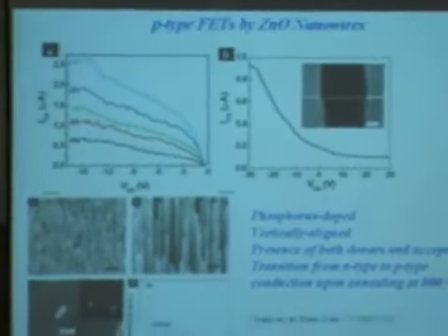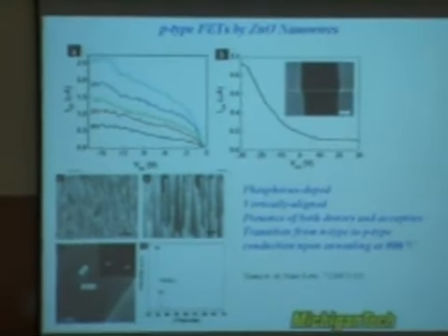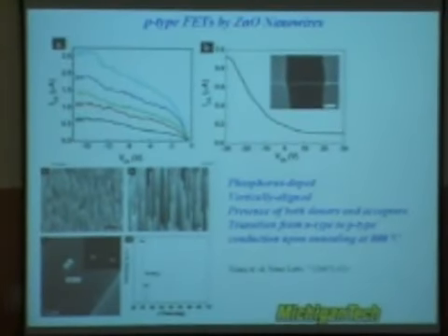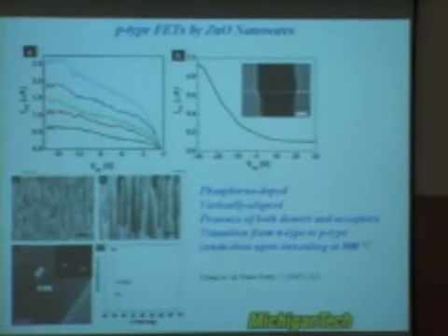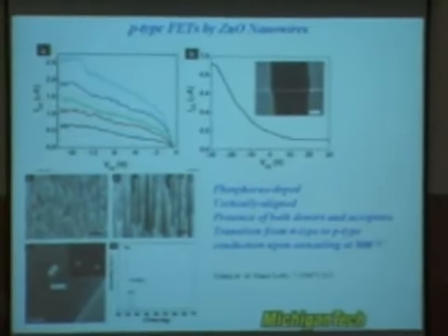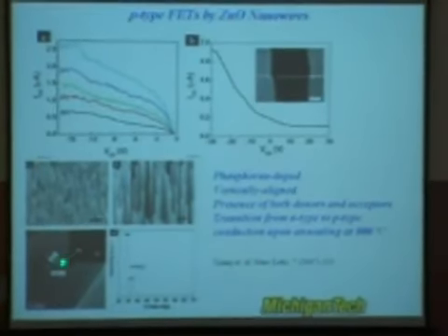And you can actually see that some of the devices demonstrated on zinc oxide always behave N-type, because oxygen tends to have vacancies inside the zinc oxide. And it's very challenging to make these P-type materials, and it was just published this year, so I'm giving you the latest information, all right? So it can be done in P-type and single crystal materials, and it shows the gate effect of the P-type materials. However, this type of P-type zinc oxide is still not very stable at this moment.